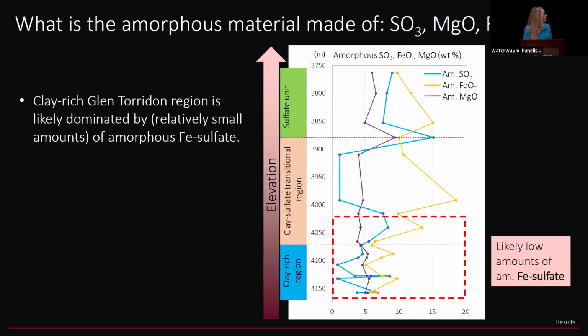The other relationship that I wanted to point out is the amorphous sulfate. The Glen Torridon clay-rich region is likely dominated by amorphous iron sulfate. And then again, I think that this shift changes, and we can see this in a lot of the CheMin data as well. It starts to become more amorphous magnesium sulfate as we begin to dry up in this region.